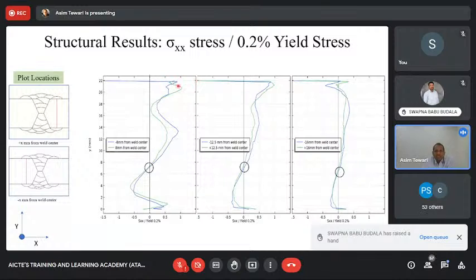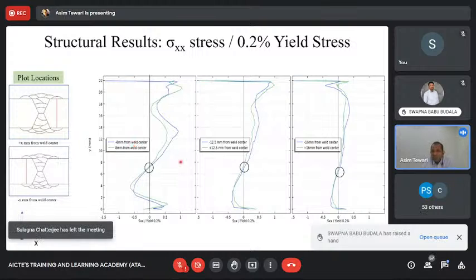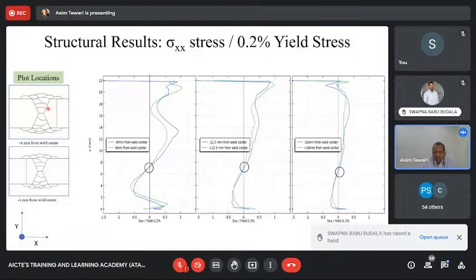And what you see is that the residual stresses are now a function. So this is basically looking at residual stresses along this line and along this line. So we are looking at the two sides. So these are those two curves. One is for one side, the other is for the other side. And what you realize is that the two are not exactly the same. If this line is very, very close, the residual stresses are higher. If this line is taken further away, the residual stresses become much closer to zero.